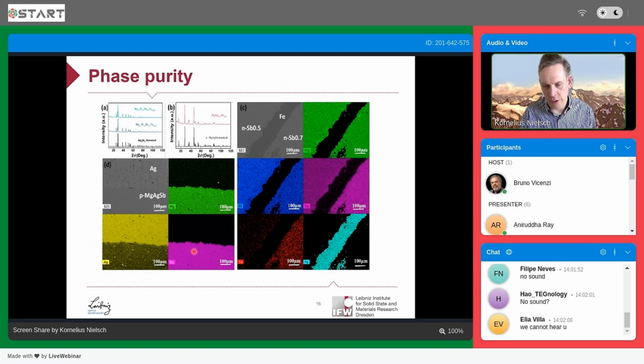Take a look here at the contact material. We can form rather well-defined interfaces. We have used silver as a contact material for the P-type magnesium silver antimonide, and for the N-type magnesium bismuth antimonide, we have used iron as a contact material. Since we have a segmented structure of the two compositions with iron in between, you can see here where the laser pointer is the transition between these two N-type magnesium bismuth antimonide materials, and in between we have the iron.